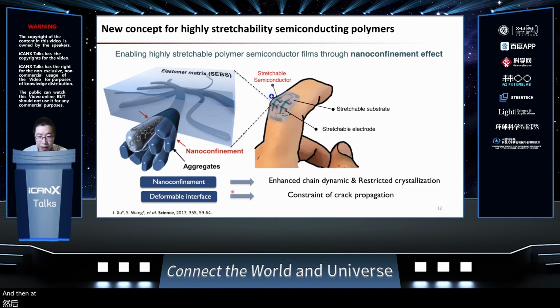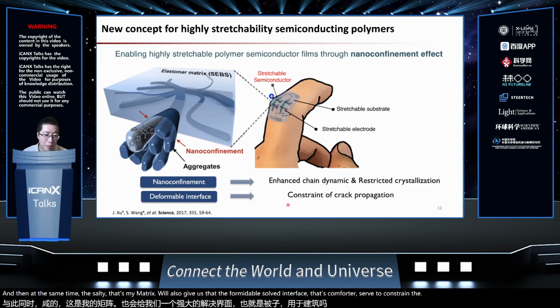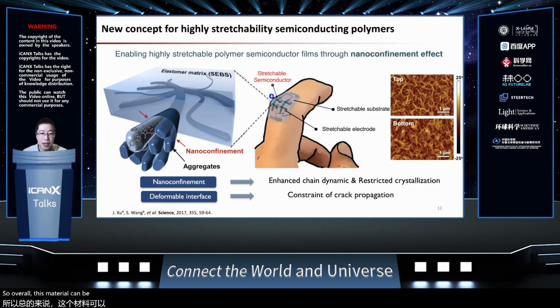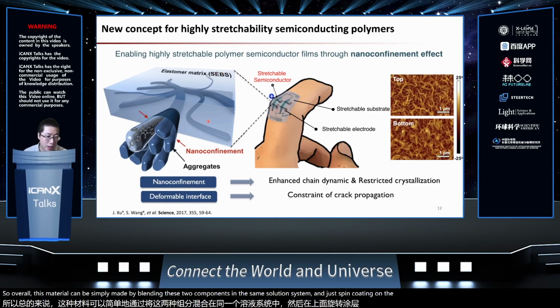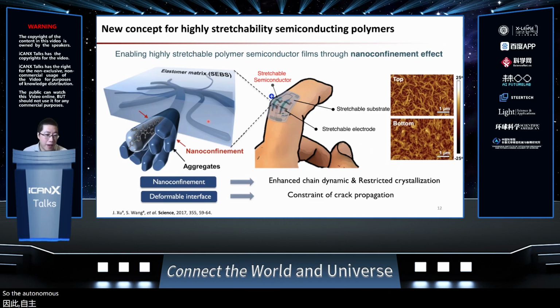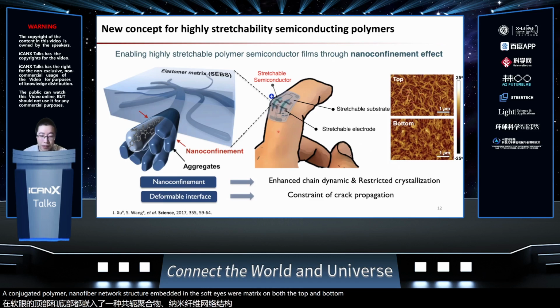And at the same time, the soft elastomer matrix will also give us the deformable soft interface that can further serve to constrain the crack propagation when the material is under deformation. So overall, this material can be simply made by blending these two components in the same solution system and just spin coating on the substrate. The autonomous phase separation process will give us the desired morphology of a conjugated polymer nanofiber network structure embedded in the soft elastomer matrix on both the top and the bottom surface of this thin film.